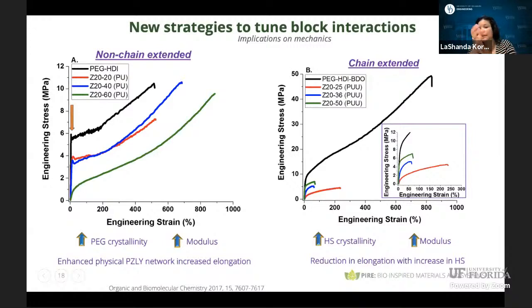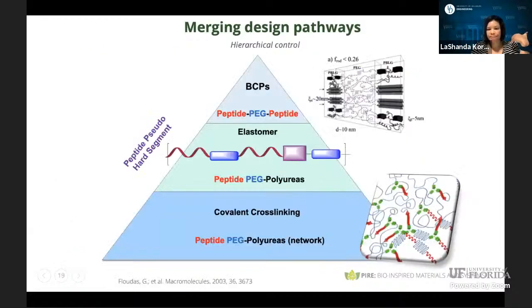For the chain extended systems, it's the hard segment crystallinity that is driving the overall modulus increase in these systems. You can see here that the highest modulus actually occurs for the control and that of the Z2050, which has this really nice hard segment crystallization peak or melting transition here. And so you do get a reduction in the overall extensibility that is really driven by this increase in the hard segment crystallinity of the system. So this really does show that with this framework, by controlling interactions between either soft-soft or between soft and hard, this allows you to control the overall mechanics of the system.